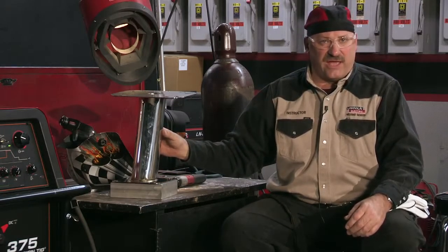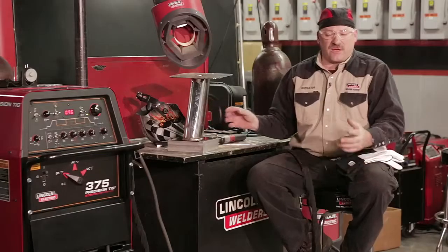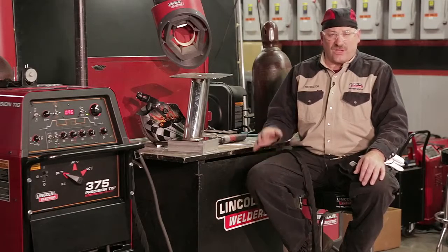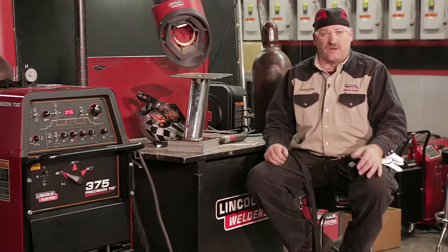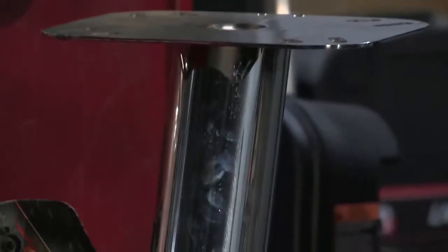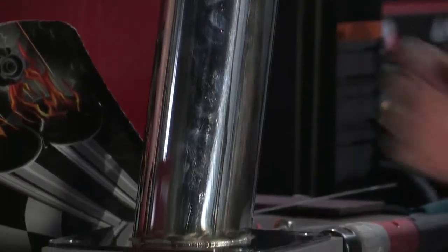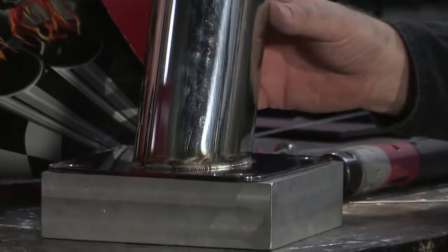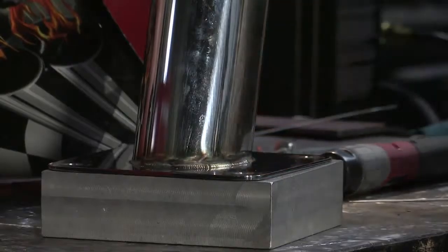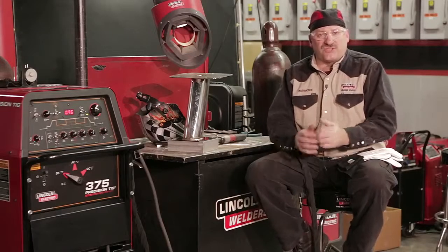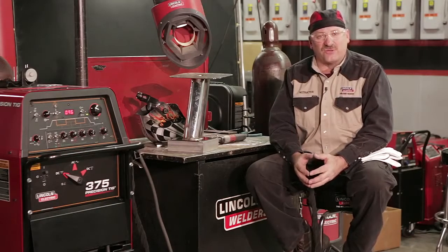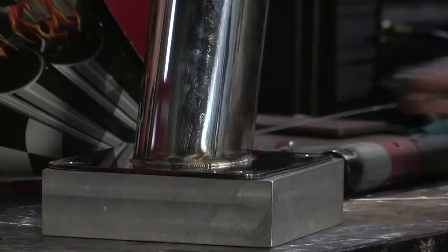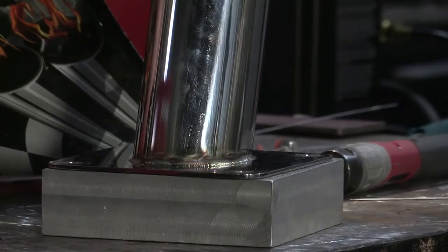This happens to be a 316L stainless, which has a little more nickel in it, but it also has some moly added to the stainless. Anytime you're within 5 miles of the coast, they recommend 316L stainless because of pitting corrosion. Also, for a lot of industrial applications, chlorine in swimming pools, they often go to a 316 stainless. Food grade, sometimes 316 because some certain acids in foods will actually pit stainless steels too. So this is a little better grade of stainless than what your kitchen sink is made out of.